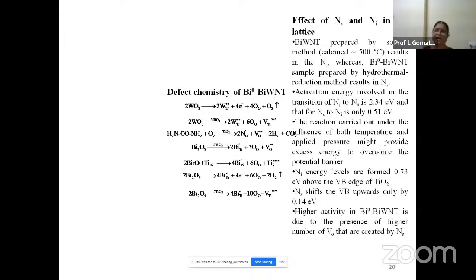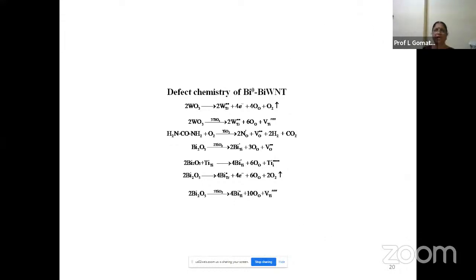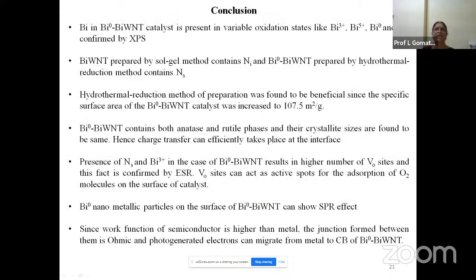The reaction carried out under the influence of both temperature and pressure might provide excess energy to overcome the potential barrier, and interstitial nitrogen levels are formed at 0.73 electron volts above the valence band, and substitutional nitrogen forms around 0.14 electron volts. This is due to the higher activity of Bi0-BiWNT, due to the presence of a higher number of vacant oxygen sites that are created by the substituted nitrogen. So I think I have told these things. Let us go to the next slide.